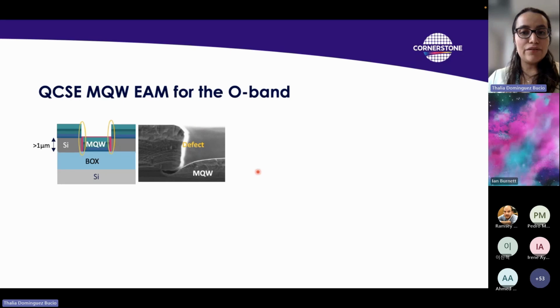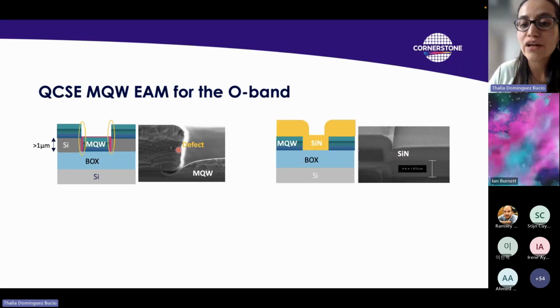Typically speaking, this has been done at 1550 nanometers, but in the O-band it's a bit more tricky because the multi-quantum wells that can work at this wavelength tend to be very thick. So if you wanted to integrate it, what you would have to do is etch your silicon, which is around 1 micron thick, and then grow this multi-quantum well of silicon germanium layers, and then create your devices. The problem is that if you do it this way, you end up with defects that make the transitions not as smooth as they could be. So one of the things that you can do with silicon nitride is, instead of trying to grow the multi-quantum well on top of the silicon nitride, start with a planar multi-quantum well stack, then etch the multi-quantum well stack, and then deposit your nitride.